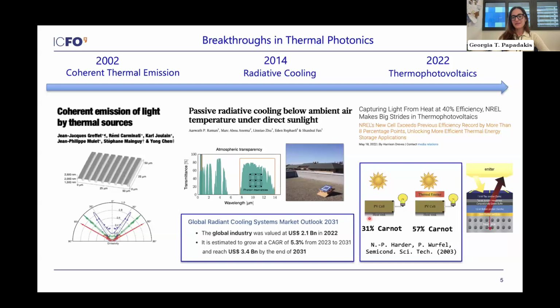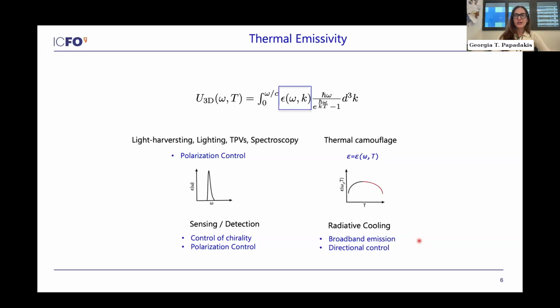So what this shows here, and these are some important numbers, is that if I take a simple solar cell, the ultimate efficiency that it can reach is 31% of the Carnot limit for these respective temperatures that I mentioned before. If I place a thermal emitter in between the sun and the PV, in this case I have a solar TPV, just by being able to control the thermal emissivity of these in-between layers, I can go to far higher efficiencies. Now, all of what I just described boils down to working and engineering the thermal emissivity of materials.